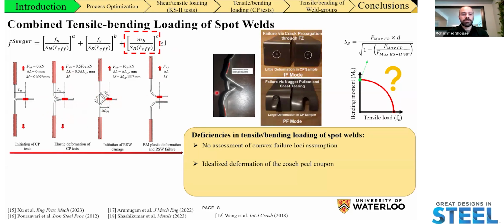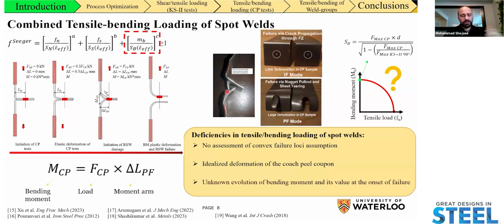But when we compare such schematics with the actual footage or images of the coach peel test, we see that they don't really go together, where we have severe amount of deformation and the rotation of the joints throughout the test. So another issue with the coach peel test is really that we are not able to comment on how the bending moment is evolving throughout the whole test. The bending moment is going to be the instantaneous load applied to the spot weld multiplied by the instantaneous moment arm. But this moment arm is going to be continuously changing from the beginning of the test to the end of the test, which is not commonly tracked in the available literature.